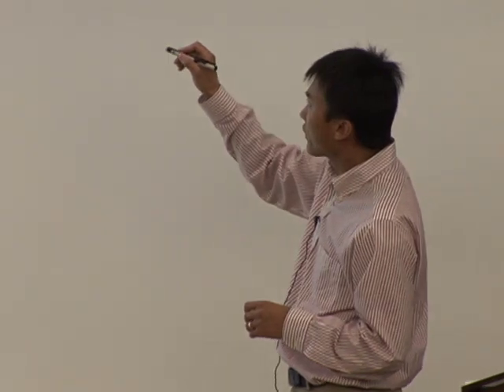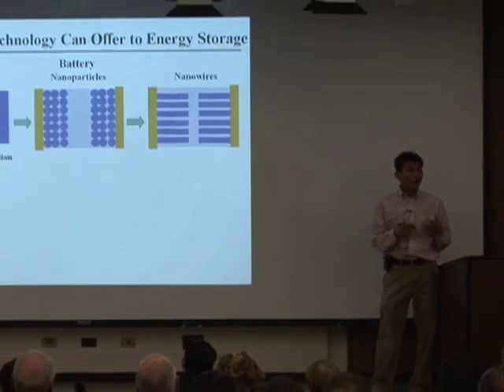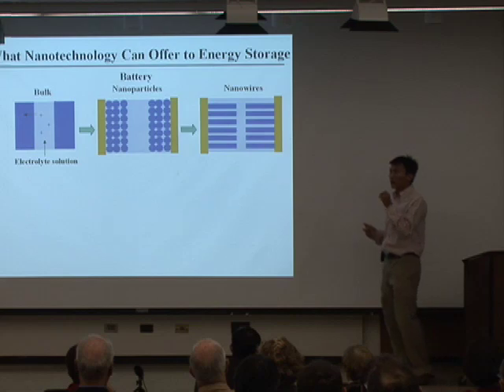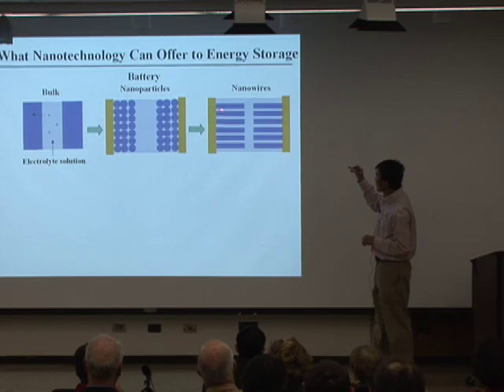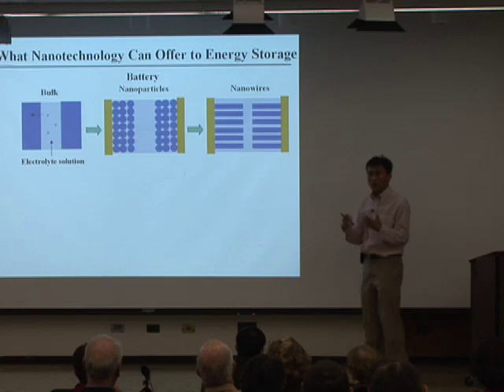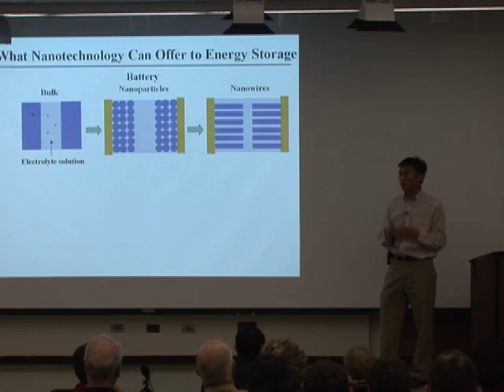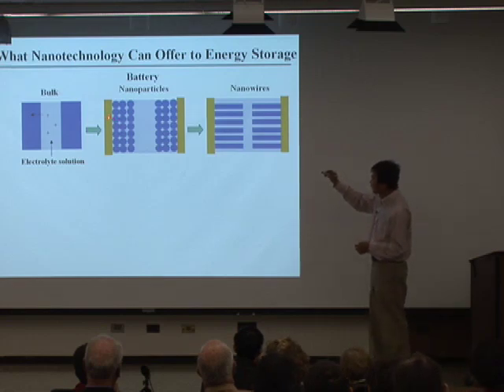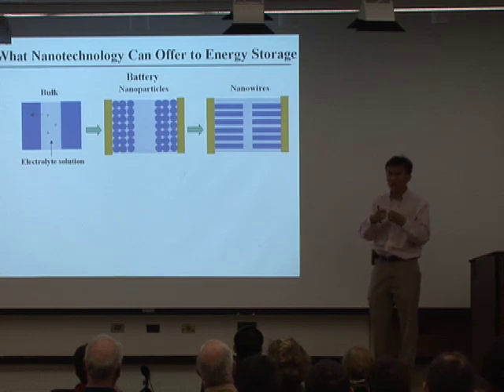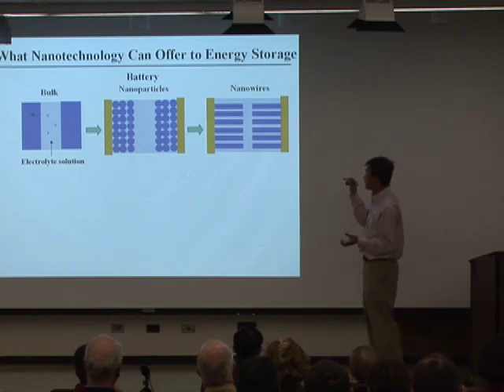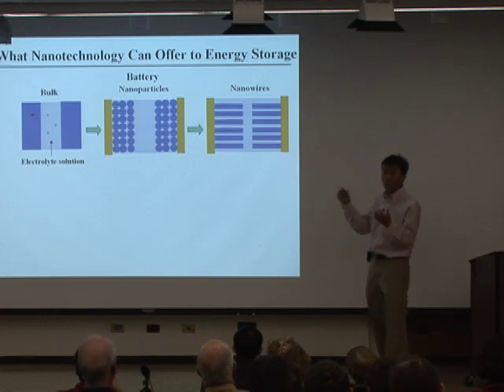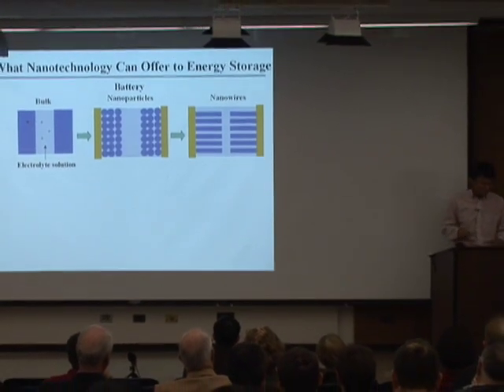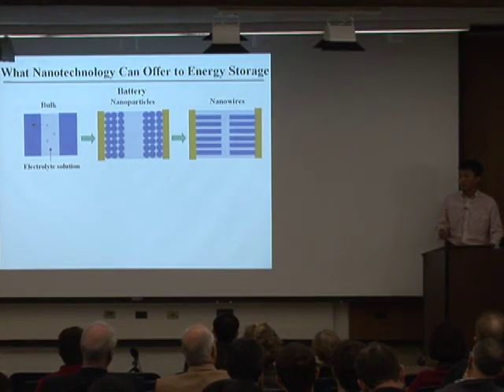So what about this? Instead of using particles, let's use another format of nanostructure, such as a so-called nanowire. This is a wire shape. The benefit you gain, not only you reduce the distance the ions go into the battery materials, at the same time, you compare with the particles, to really use the batteries, you not only need to move ions, you also need to move electrons. So in this case, electrons need to shift from the metal electrode going into the particles. This needs to hop because between particles, there's a particle resistance right there at the interface. So it's not that efficient. Now you go to nanowires. This is like a highway, it just goes in very fast. It looks like you can use the nanowires to improve both ionic conductivity and electronic conductivity.